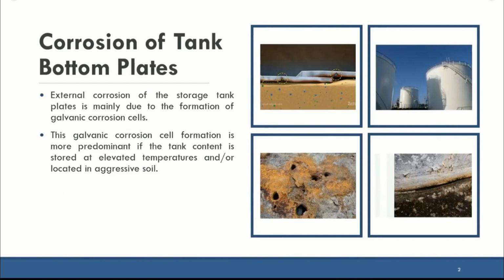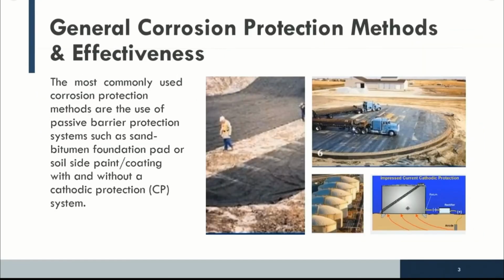So when we look at our onshore production facilities, one of the bigger challenges we face in our maintenance and reliability programs is the soil side corrosion of our above ground storage tanks. This area is very difficult to access, and as a result, it's difficult to monitor and implement corrosion mitigation systems for the underside of our tanks. When we look at the systems that we typically use today, there's a few ones that you will see common: cathodic protection, vapor corrosion inhibitors, and different passive barrier systems that could be traditional coating systems as well.